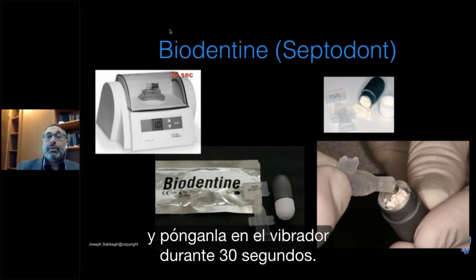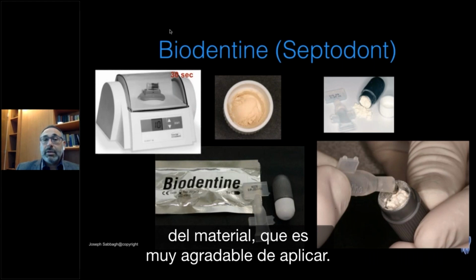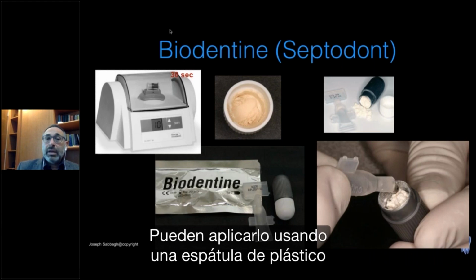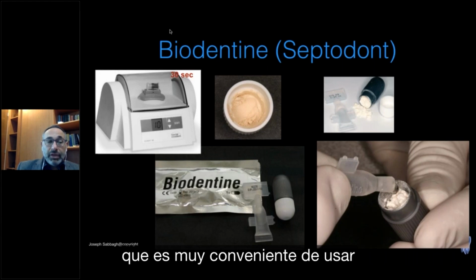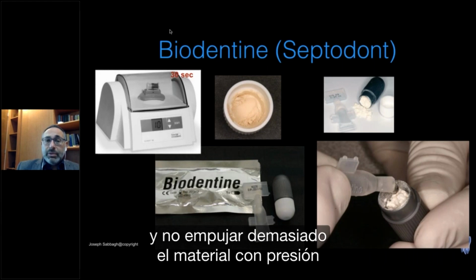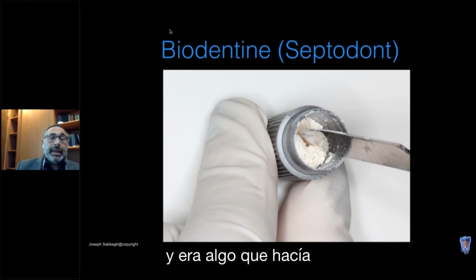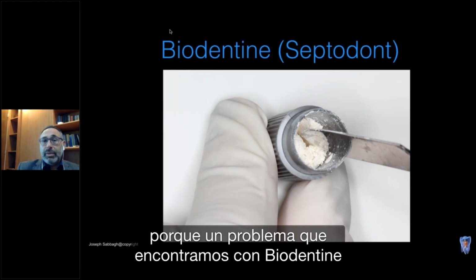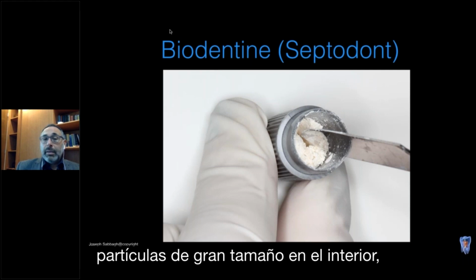And once you open it, you need to have a creamy appearance of this material that is very nice to be applied. You can apply it using a plastic spatula, or you can apply it using an amalgam carrier that is very convenient to use. But you need to be very gentle not to push the material too much with pressure, mostly if you have an exposed pulp. This is another trick also, and this was something that I was doing, because one problem that we found with the Biodentine in the early version was that sometimes this powder contained big size fillers inside, and this was due to the manufacturer.